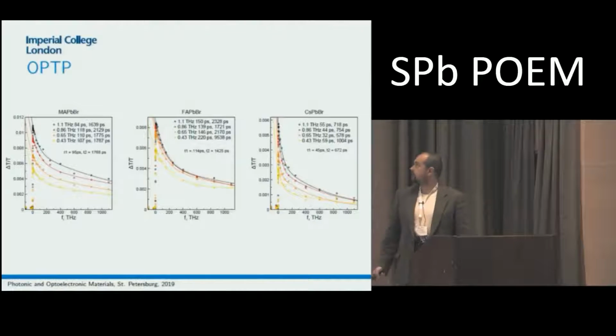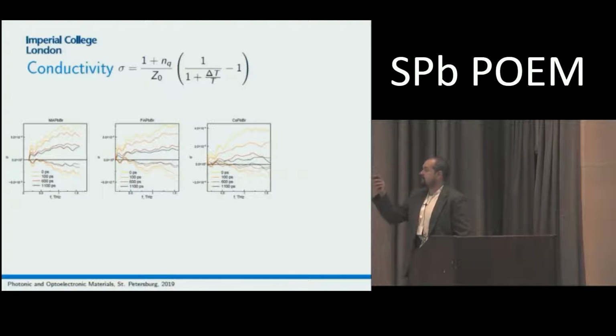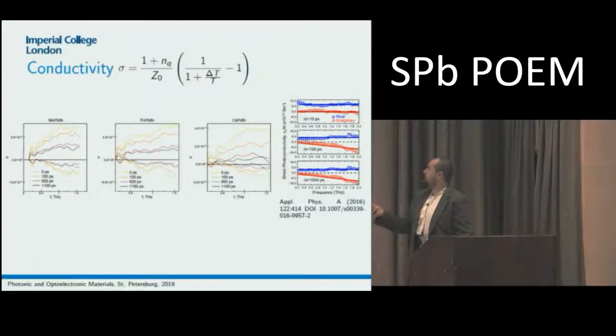We still need to analyze this more thoroughly and work with theoreticians to build explanations for this. But this is quite repeatable. We can see this in numerous measurements, and further we will see that cesium actually reveals stronger couplings that are measured directly. So yeah, this is the conductivity derived, and again the conductivity drops in time quite fast, and this is in good agreement with previous publications on the photoconductivity in these materials.